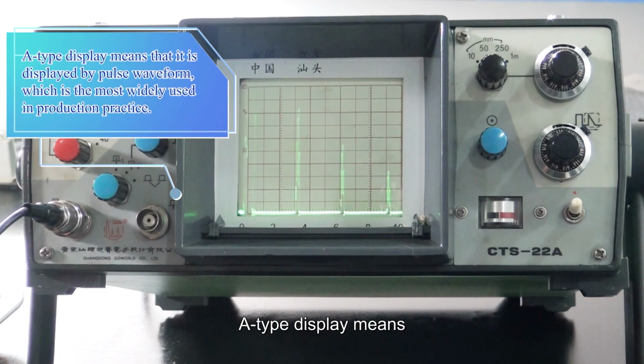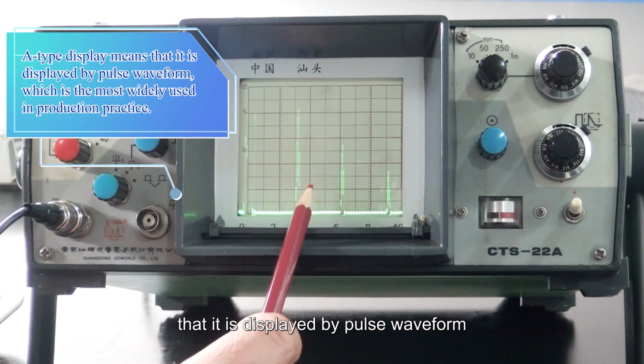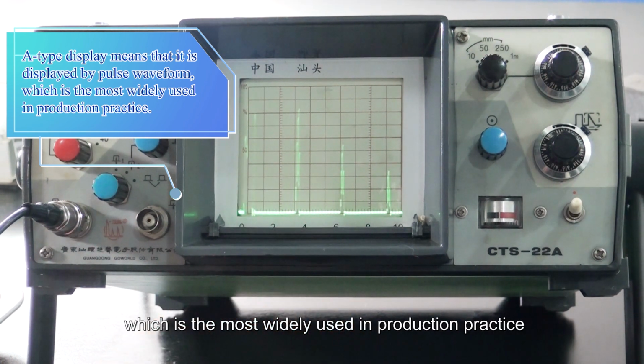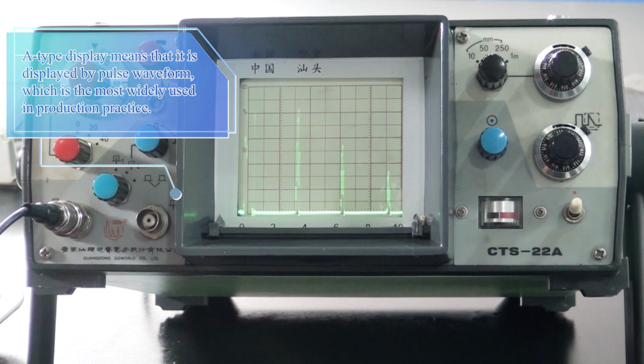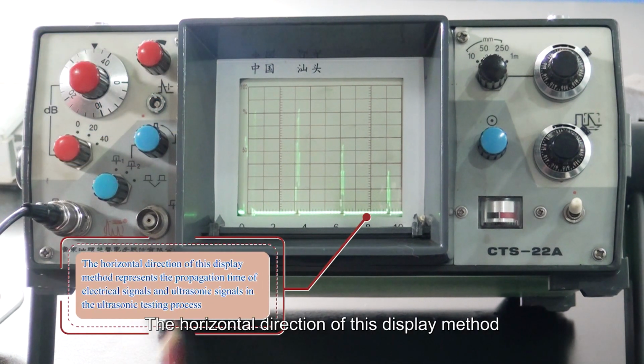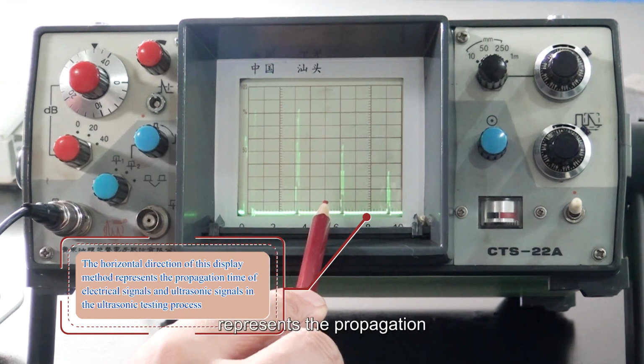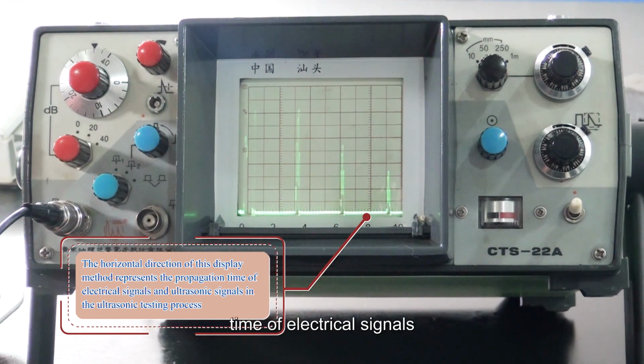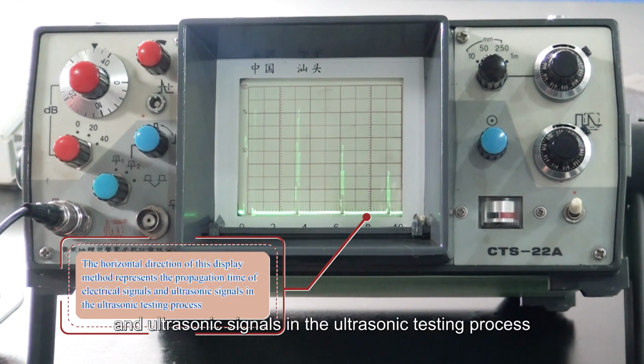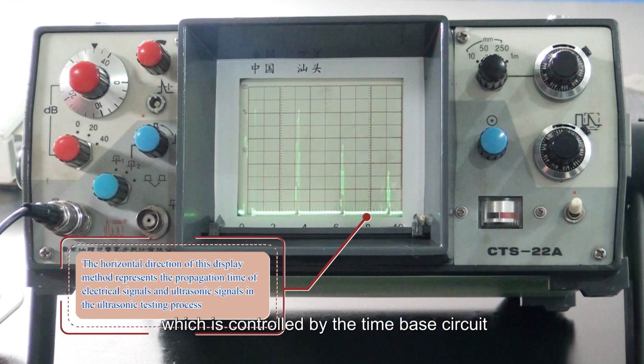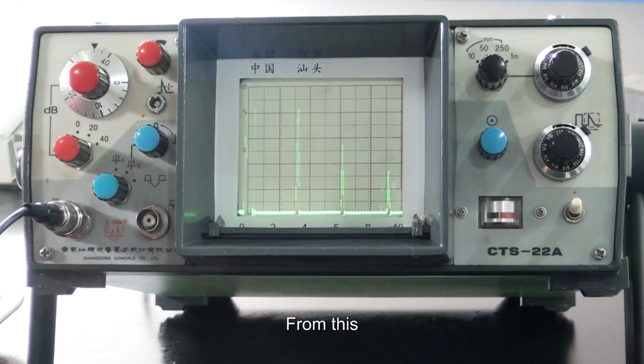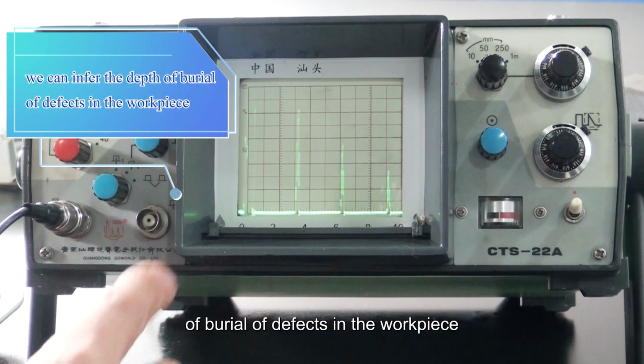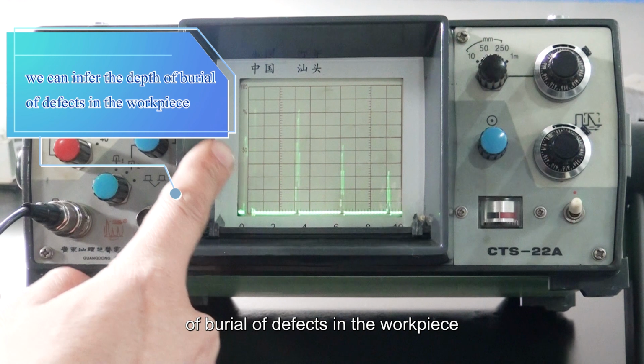A-type display means that it is displayed by pulse waveform, which is the most widely used in production practice. The horizontal direction of this display method represents the propagation time of electrical signals and ultrasonic signals in the ultrasonic test process, which is controlled by the time-based circuit inside the instrument. From this, we can infer the depth of burial of defects in the workpiece.